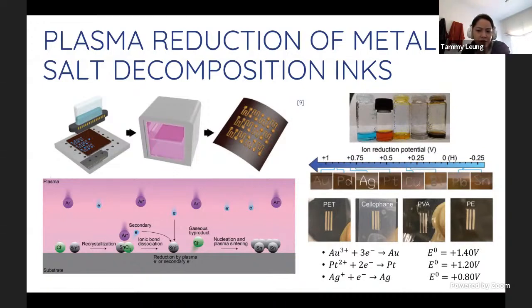The combination of this type of ink with plasma allows for facile thin film development on low temperature and non-conventional substrates. And the energy needed to convert the salt ink is solely based on the ionic reduction potential of the metallic cation, where a positive value indicates the ease with which you can do this. So taking this into account, we chose highly positive metals, which here are gold, silver, and platinum, to see how they would convert using oxygen plasma itself.